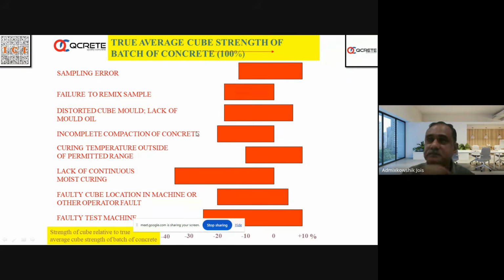Incomplete compaction. Every 1% of air which is not removed from the body of concrete during compaction is a result of sometimes somebody not giving proper strokes. The IS, we have to note, says that when we are doing casting of concrete, minimum 35 strokes. So you have to do 35 strokes minimum, and then the strokes have to be distributed properly, and you have to use strength, not just touching the concrete. And when you are casting in 3 layers, when you are casting the second layer, the rod with which you are casting should just touch the first layer, and there should be connectivity. Means it should be continuous. If you just poke without any strength, that is not vibration. You are not removing air.